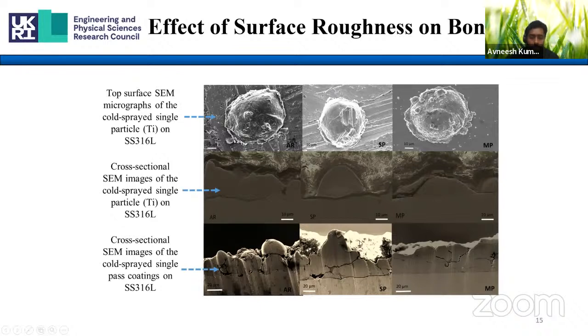The reason behind it was that in as received substrate surface, the peaks and valleys are higher and deeper. So these peaks and valleys restricted the deformation behavior of the particle. In the case of semi-polished substrate surface, the peaks and valleys were smaller in size, but large in number. So when the particle impacted with very high energy onto these peaks and valleys, all the energy of the particle is absorbed by them, because of which the particle was not able to deform. Also the contact area was minimum in this case, because the contact of the particle was with the peaks.